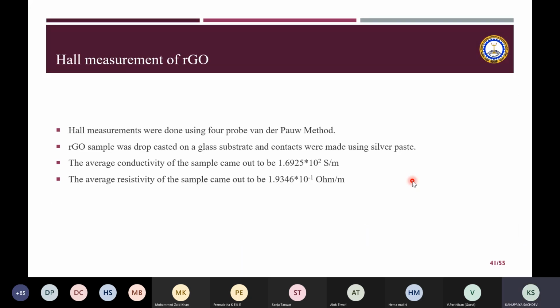So what we did was we tried to find out the electrical transport properties of the RGO, and the Hall measurements we did using the four-probe van der Pauw method. This RGO sample was made into a solution and drop casted on a glass substrate. The contacts were made using silver paste, and the average conductivity came out to be 1.6925 times 10 to the power 2 Siemens per meter, which is not a very good conductivity.